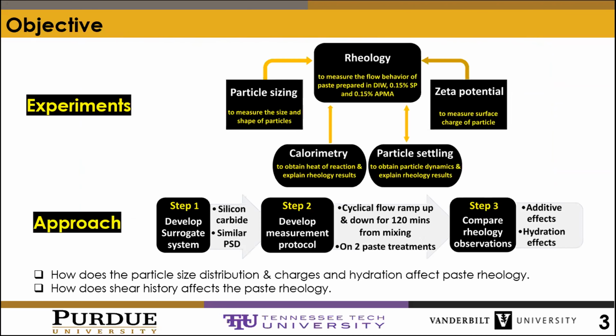So what is my approach? I looked at the rheology for two particle types, but in three different dispersive media. One which is water, and the other two, 0.15% superplasticizer and 0.15% ammonium polymethacrylate, in order to study rheology as a function of the two additives. So we compare a non-reactive surrogate to reactive cement.